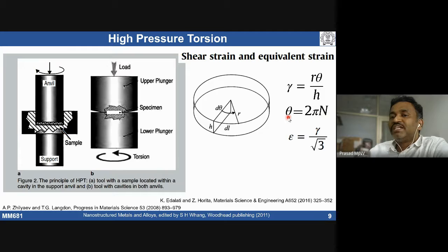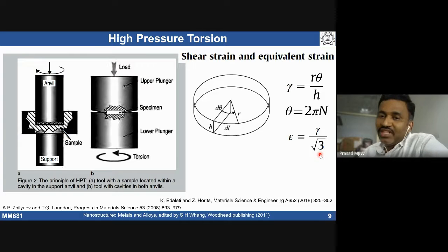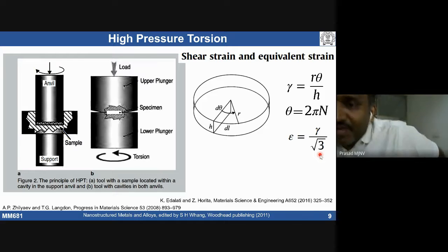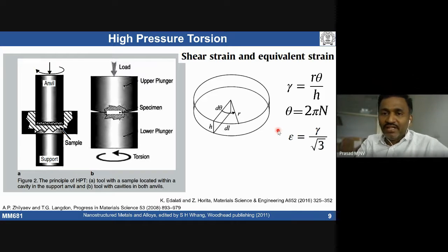That gives you the twist angle, and the shear strain at any given location at radius r. Here r is the radius, theta is the twist angle, and h is the thickness or height of the specimen. The equivalent strain can be obtained from the shear strain gamma by dividing by root 3. So when you deform a material under torsion, your strain is going to vary from the center to the surface, or periphery, of the disc.